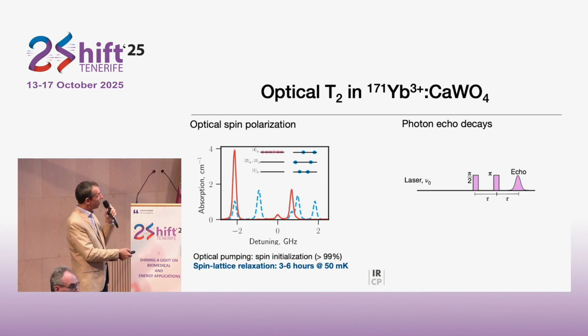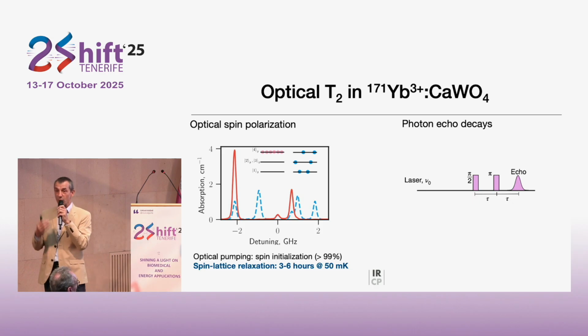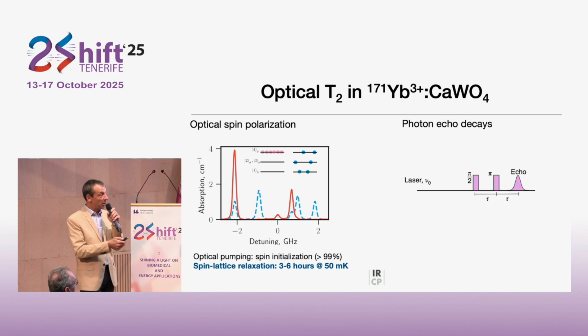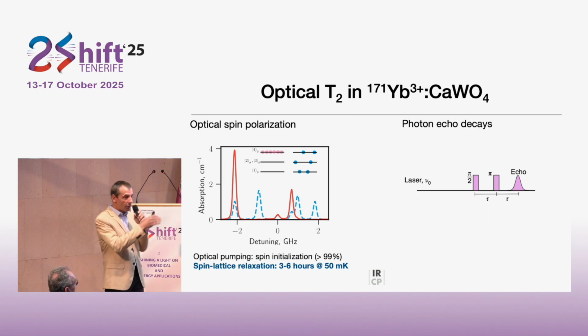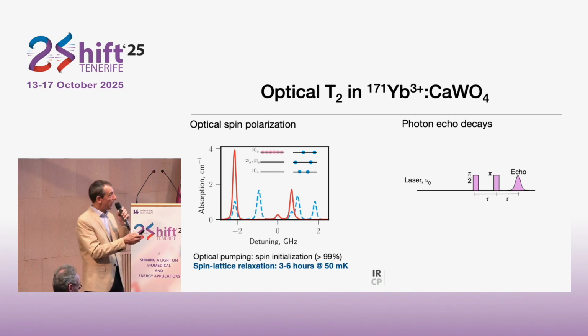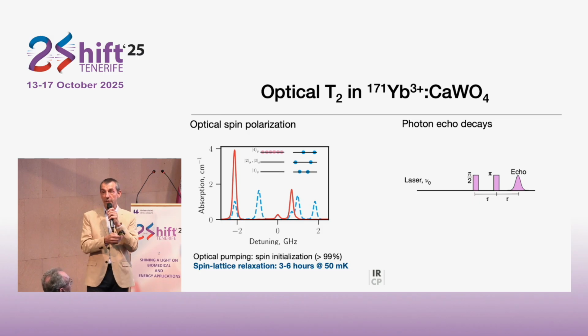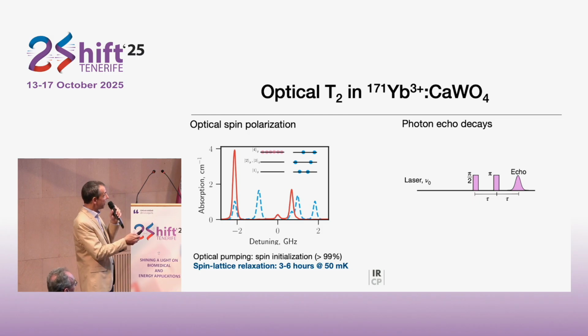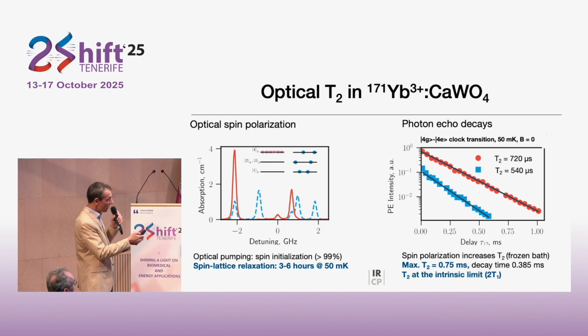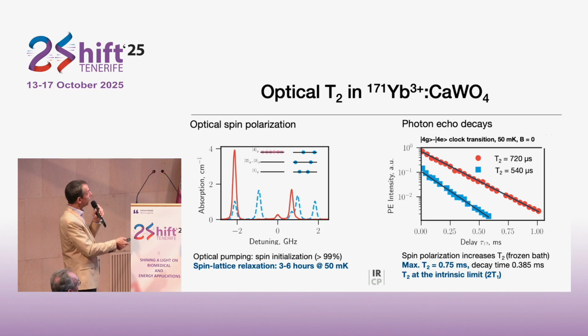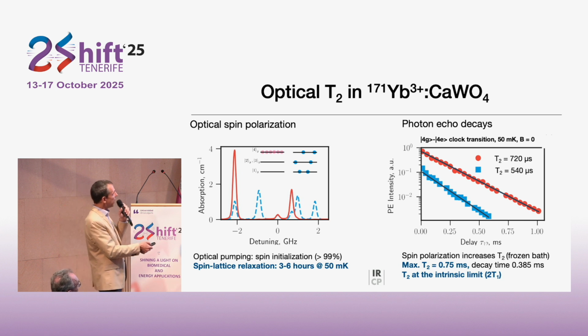And so if we increase the delay now between the pulses, you will see the intensity of the echo going down simply because we have more and more ions which have been perturbed. And from the rate of this decrease of the photon echo intensity, we can directly determine the quantum state lifetime. And so this is what we did here. You see the photon echo intensity as a function of the delay. Here we have simple exponential decays. And we have two situations.